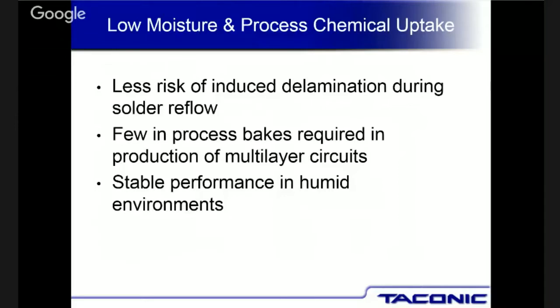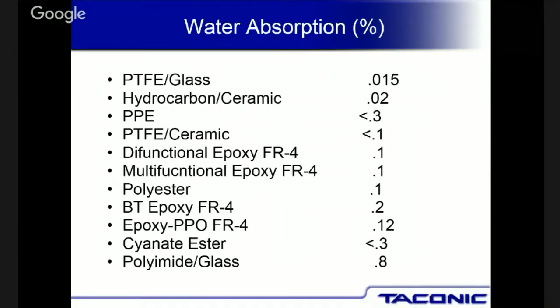And by the way, this is one of those things that I find amusing, because there is no such thing on a data sheet as chemical absorption. Everybody's data sheet talks about moisture absorption, which is basically water. And most of these materials have water absorptions which are pretty low. You look at the first one there, PTFE glass, we're looking at 0.015%, which means it's not going to pick up any moisture.